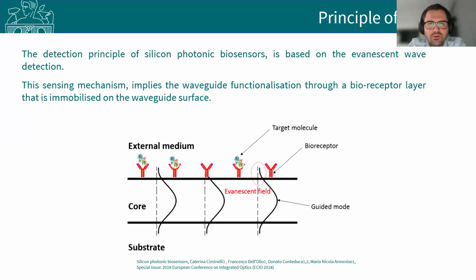The detection principle of a photonic biosensor is based on evanescent wave detection. This sensing mechanism implies the waveguide functionalization through a bioreceptor layer that is immobilized on the waveguide surface. So here we have the core of the waveguide, and on the top and on the side of the waveguide there is a functionalization, so bioreceptors are added, which catch the target molecules. Because in the liquid the concentration of the target molecules is typically quite low, it would not be possible to detect it by the light. But if we increase the concentration in the area of the waveguide, the refractive index surrounding the core is changed due to the bigger number of target molecules.